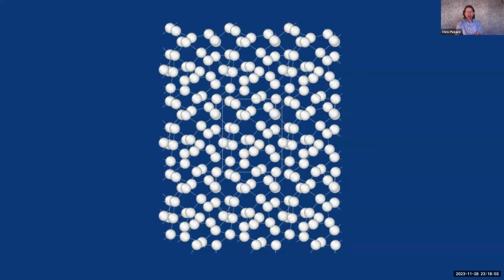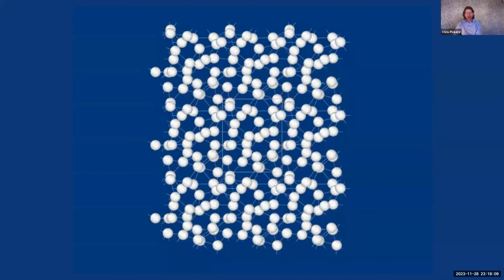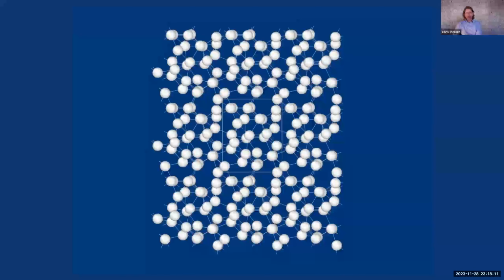And so this might be an initial random structure, and then you feed that into a code like CASTEP, your favorite DFT code, and tell it to relax, and that structure moves downhill until it can't go downhill anymore, and then you're stuck in a local minima. And you can see that this final structure doesn't look much less random than the initial structure. What we found is something like an amorphous form of boron.